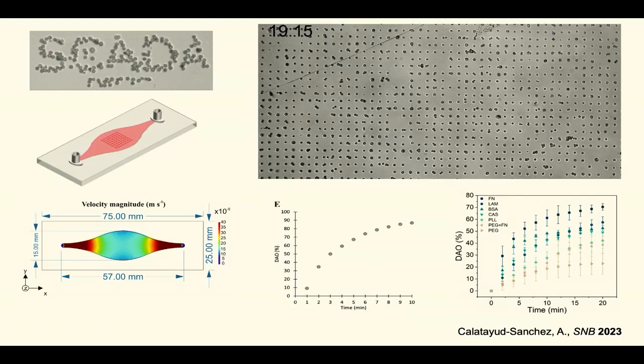What we are actually measuring is cell capture by the matrix, but eventually we could also start to study cell adhesion effects. And we also applied this device to measure cytotoxic effects. So once the whole array is filled, if you expose that array to a toxic compound, what happens is that the cells detach. The same way that I can quantify how they are adhering, I can also nicely quantify how they detach. The more toxic, the faster they die, the faster they empty the array. So this is a cartridge that people could use to study cell adhesion, cell affinity for different matrices, or cytotoxicity of different compounds.